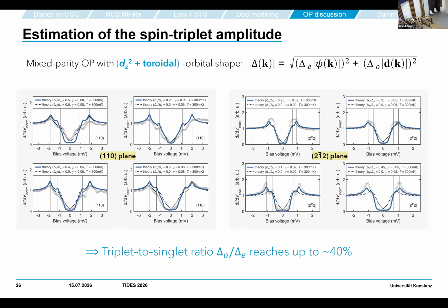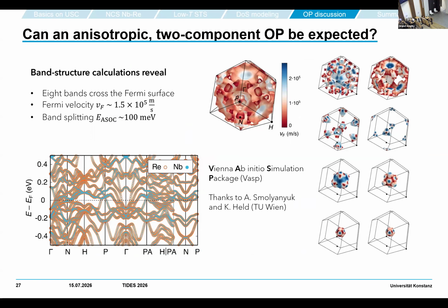If you do the analysis, what we find is that the whole zoo of our spectra can be described with ratios between the odd triplet component and the even singlet component, which is on the order of 40%, with some variation between 30 and 45 or so. It's not a tiny admixture—it's really a large contribution.